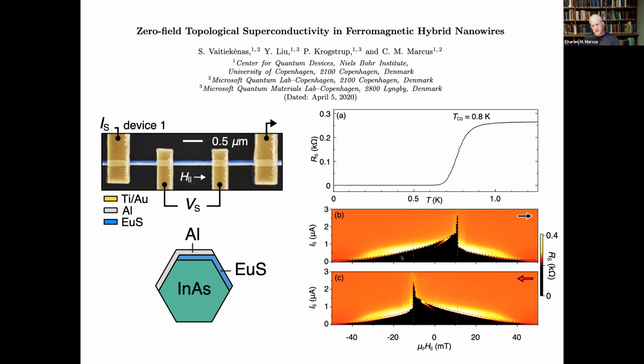Now, the interesting picture to see is how that critical current at which the system becomes normal changes as the external magnetic field is swept. Again, nothing about the inside of the nanowire, it's just like a bridge for it at the moment. The critical current of the outside of the system, as the magnetic field is swept to the right, as the magnetic field is swept from far negative to far positive, it rises, it reaches a peak, and then it quickly and discontinuously falls, and then continues to diminish until the critical current vanishes at about 50 millitesla applied magnetic field.